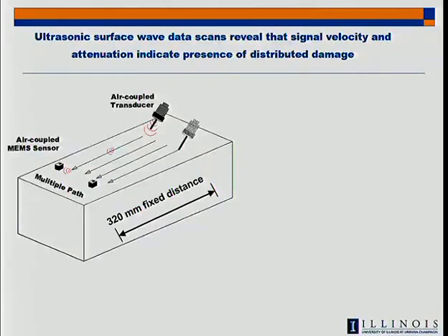So now that we have a system where we have a sender and a receiver at some distance apart, we can send and receive. And because they're not touching, we can move them synchronized together and get a series of rays of information parallel to each other and stack them. So we get some information about that. So we scan and we're just continuously collecting data. So imagine that's in real time. We're going across and we're continuously collecting. The speed at which we collect is very fast. It's on the order of electronic processes, much faster than the motion that we could ever get with the scanner physically moving it. So that's not a problem.